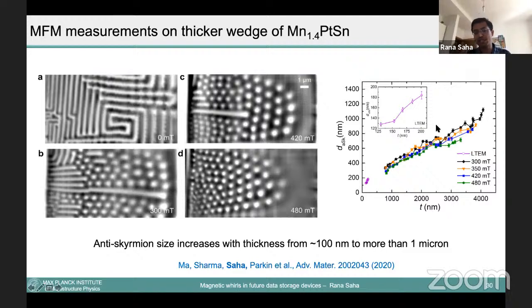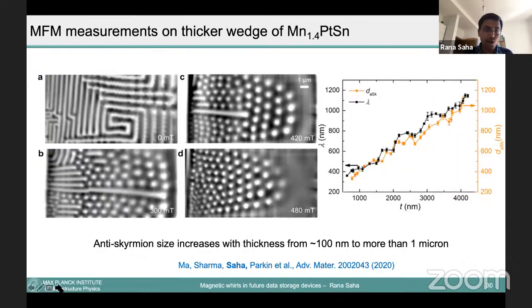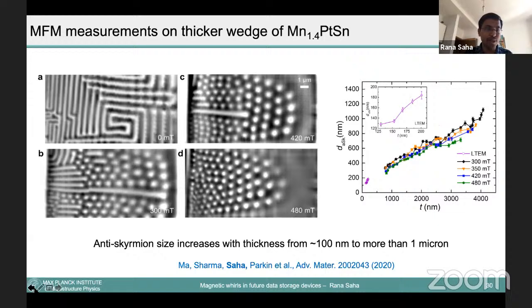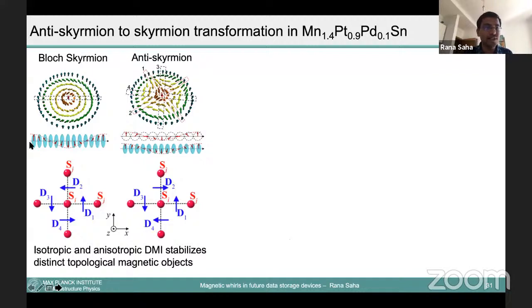So if you want to make a device, you must know at what thickness how much skyrmion size there is, and how much the density is. So if I have a map of this, now you can make the material and do this investigation. And also these are the antiskyrmions. In the same material, you can go from, for example, antiskyrmion to some kind of skyrmion material.